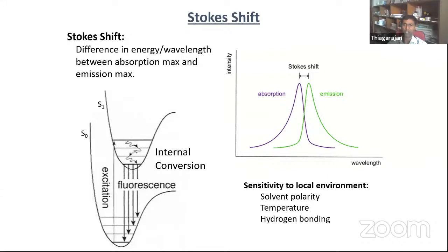Solvent polarity: if the molecule contains a donor and acceptor, charge transfer normally occurs. The electron shifts from the donor to the acceptor in the excited state. So the donor is delta positive in the excited state, and the acceptor is delta negative. If I use a more polar solvent, it will stabilize the charge transfer. Stabilization means lower energy, which means higher wavelength, so we will have a more red shift. For example, if I dissolve a very polar probe in toluene and DMSO, DMSO is the more polar solvent and toluene is the less polar solvent, and both are aprotic solvents. Aprotic means they don't have any acidic hydrogens. When we dissolve the probe in these two solvents and measure, DMSO stabilizes the charge transfer better than toluene. So in toluene we can see the emission in the blue region, and in DMSO we can see the emission in the red region.